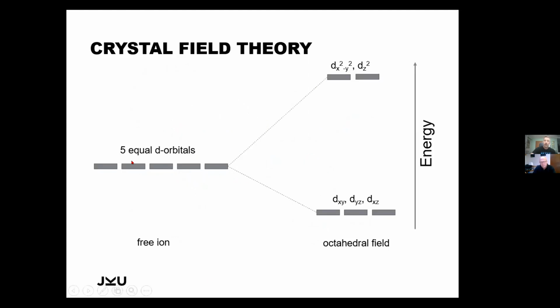And this crystal field now brings us that in a free ion we have 5 equal d orbitals, and these equal d orbitals are now split up in 2 sets. You see the dz squared and the dx squared minus y squared, which are perfectly along the x, y, and z axis. Therefore, they have a higher energy because electrons are negative, the oxygens are negative, so they have some pushback mechanism and the energy is increased here. On the other side, the d orbitals which are in between the oxygens have a lower energy.